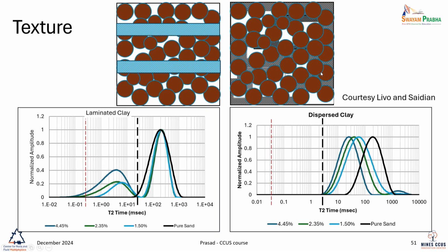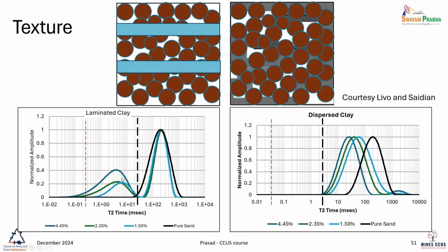If we mix it, this is the sand, and we mix it, now all of the pore spectrum shifts. We start getting large pores, but in that large pores, they are compromised by the presence of clay. And so when we examine pore structure, this would be one hydraulic unit, and this would be a very different hydraulic unit. Right? So when we are looking at compressibility, becomes really interesting, because this would have a very different compressibility.